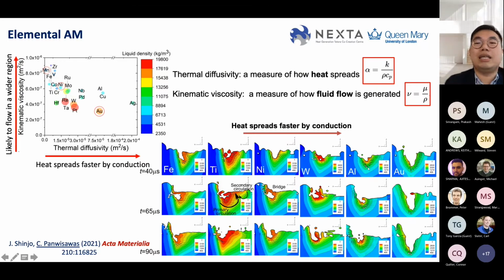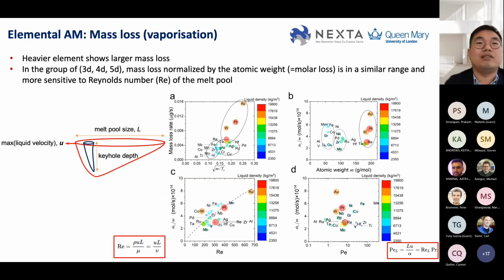You will see that the characteristic to represent the additive manufacturing process has been captured using a chemistry-process relationship here. And then you will see that gold, as I said, spreads faster by conduction. But again, the fluid flow, which is actually less viscous than manganese or nickel, for example, that generate keyholes, compared with some other material like titanium, where porosity only takes place, for example. I mean, all these things have been summarized into a diagram we call the elemental AM